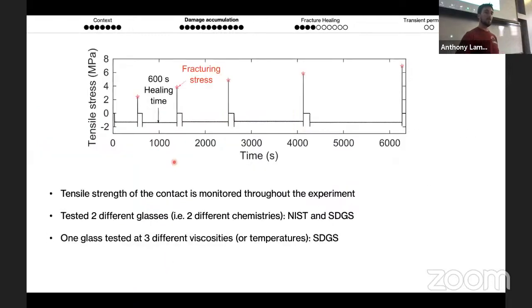During this, I'm going to look at the peak stress that's being generated by the contact. And I've done that on 2 different glasses, and they are standard glasses so that we have well-constrained chemistries. And then I've tested one of the glasses at 3 different viscosities, so 3 different temperatures.